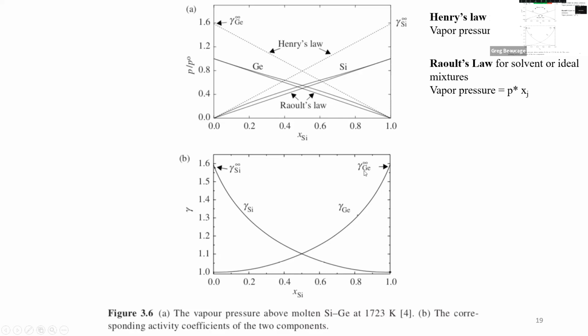Because you're making silicon and germanium into a diamond cubic crystal. So you're making a solid solution, so they can substitute for each other. They're about the same size. I think if they're within like 10% of the size of the other atom, they'll fit into the same crystal structure. So both have diamond cubic structures, so they can mix in the same crystal. So you can get an alloy of those two in the same crystal. You can figure out this gamma infinity for the two, but if you have one of them, it must be related to the other one. That's the issue.